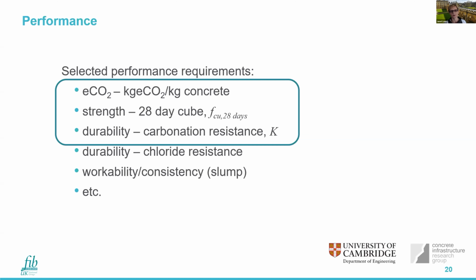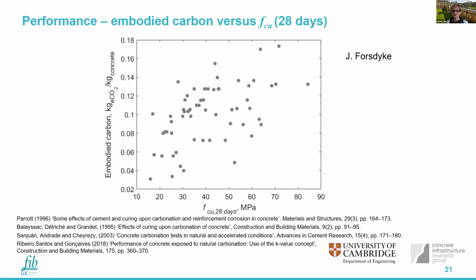And I'd like to pick up a little bit of how we've started to look at these multiple dimensions in the context of these three particular performance requirements, the ECO2, strength, and carbonation resistance. So this is work from Jessica Forsdyke, again, another of my PhD students. What she's done is she's looked at a number of papers in the literature, and she's extracted the constituent materials from those studies, and also their measured cube strengths. She's then calculated what the embodied carbon is. In this case, it's kilograms ECO2 per kilogram concrete, and that's the vertical axis, versus the concrete strength. And you see we get a scatter of materials.